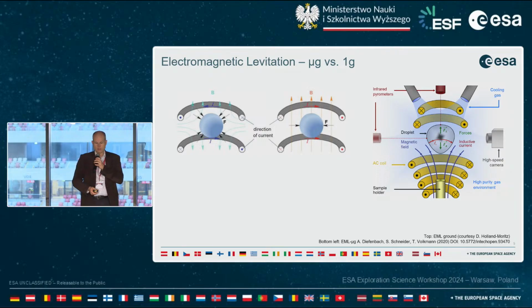If you go to space, that's on the left-hand side, the coils look different. It's two sets of coils, and you use different fields. You use a quadrupolar field to position the sample that causes no fluid flow inside of the sample, and you use a dipolar field that is then switched on in order to heat the sample. That induces, of course, fluid flow again inside of the sample, but when you switch it off and you look at the cooling of the sample and measure properties during cooling, then the fluid flow is minimized.